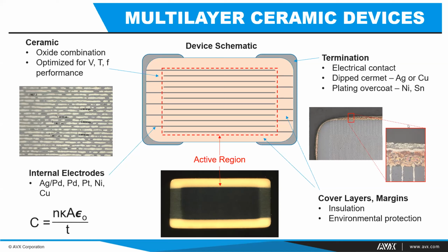The nickel acts as a barrier which prevents dissolution of the base material into any soldering that happens, and then the tin provides an oxide barrier or a prevention of the nickel from actually being oxidized, and so we coat that with tin. That's also a very wettable surface that works most well in most soldering operations.